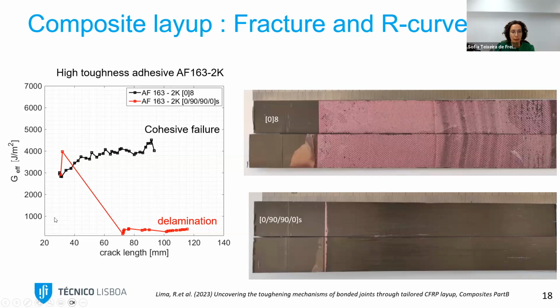When we look at the energy that is necessary to grow the crack in the specimen, we see that there is an increase in the resistance to damage in the initiation. At the beginning there is a little bit of increase, but once the crack advances a bit further, there is a huge decrease because of the delamination in the composite. Now we didn't understand this, because delamination in composite is known to be very, very weak. It's out of plane properties, but we didn't understand exactly why there was this increase in the damage initiation resistance.